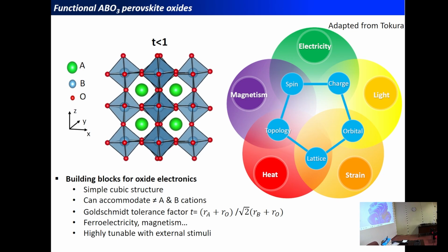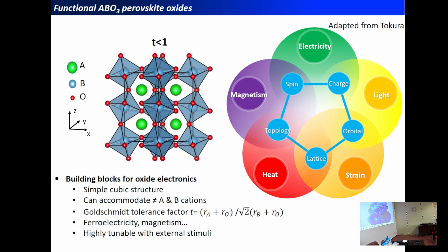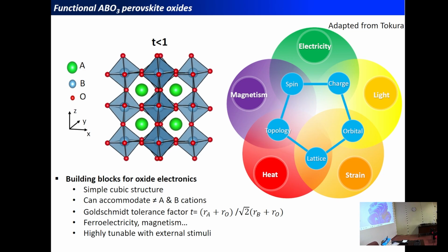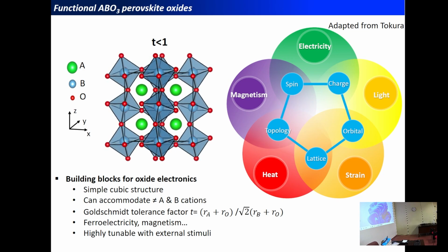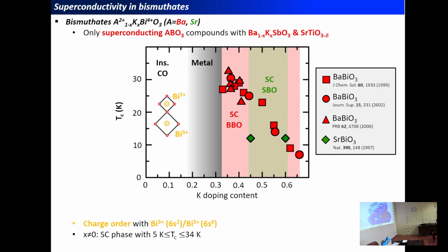As I've been working on perovskite systems for 15 years, I was looking for systems which show superconductivity. If we look in the literature, there are only a few systems that are reported to be oxide superconductors with the ABO3 structure. This is the case, for instance, of the bismuthates, with barium or strontium on the A-site cation, but also the antimonates, where bismuth is substituted by antimony, or also oxygen-deficient strontium titanate.